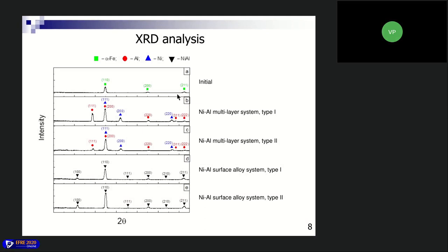So as we look at the X-ray diffraction analysis, for the initial material we can see only the iron. For the nickel-aluminum multilayer system type 1, we can see the peaks of nickel and aluminum. Also, quite the same picture for the system type number 2. And for the surface alloys, we can't see the peaks of aluminum and nickel, but we can easily see the peaks of the intermetallic nickel-aluminum alloy.